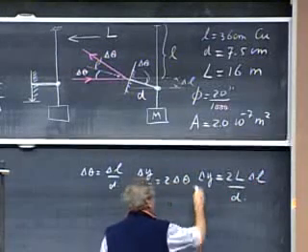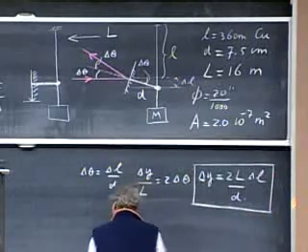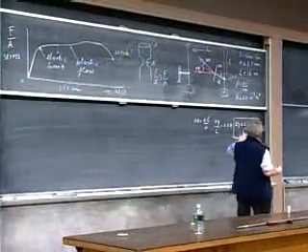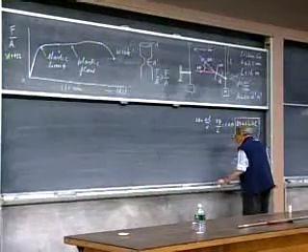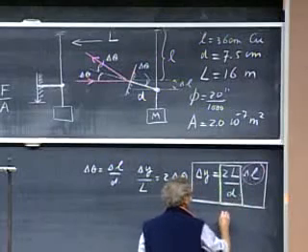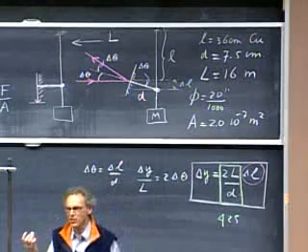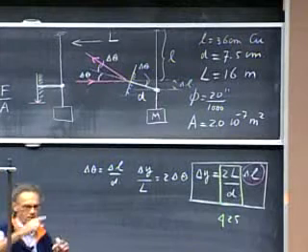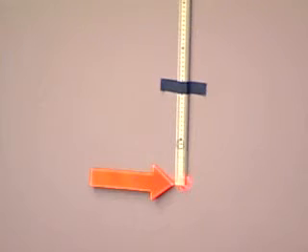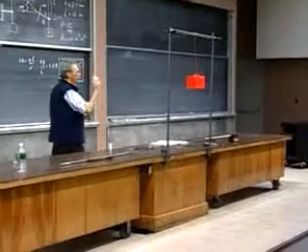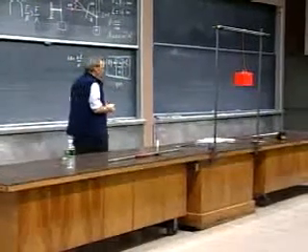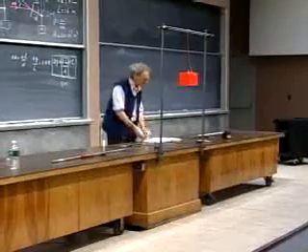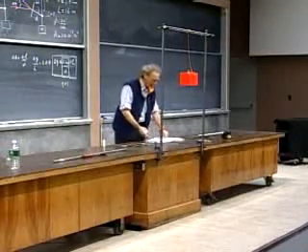2L times delta L divided by d. And look what we have done now. We have converted something that is immeasurable, delta L, which is fractions of millimeters, to something on the wall that we can measure, because this ratio 2L over d, in our case, for the dimensions that I have chosen, is about 425. It's like a magnification factor. So if we see a displacement of that laser beam on the wall of 40 centimeters, which is easy to see, it means that the wire got longer by only 1 millimeter. So 40 centimeters there translates to 1 millimeter there. And if we would see that laser beam go up 4 meters, it would mean that the wire would only have become 1 centimeter longer. So it is a wonderful way to magnify the effect and to measure it.